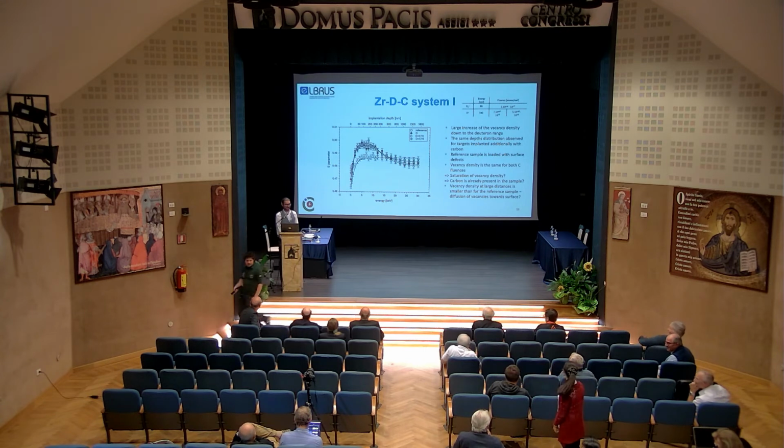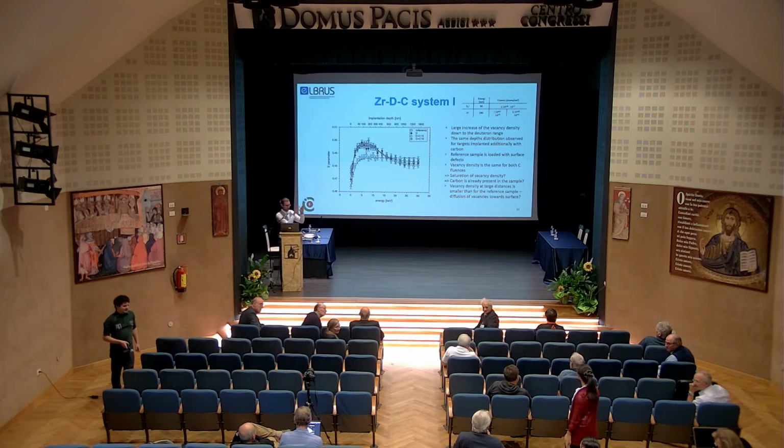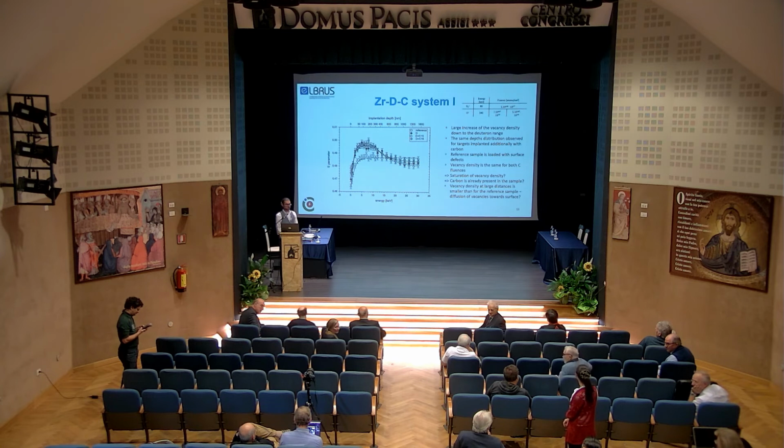The main contribution to the screening is coming from the conduction electrons. So it's not all the zirconium electrons, but there is maybe 10, 20, 30%. It depends on the hosting metal, and there is a polarization of the bound electrons of zirconium of these hosting atoms as well. So we see both.